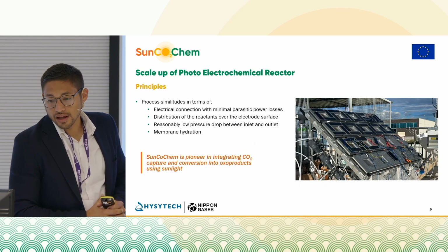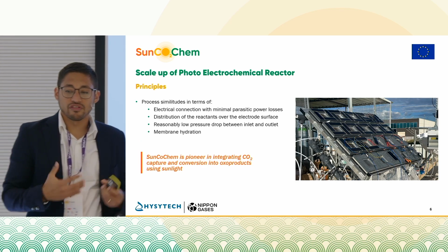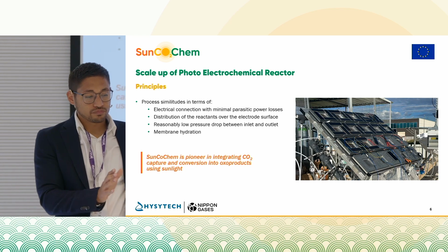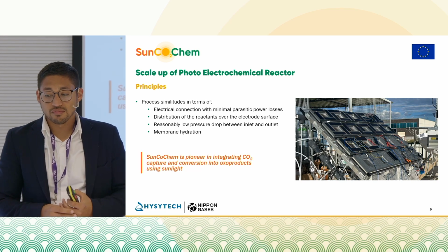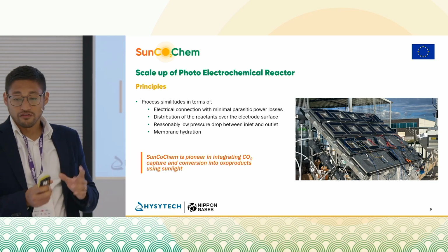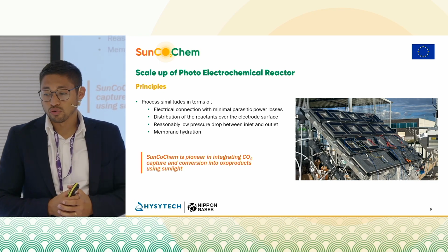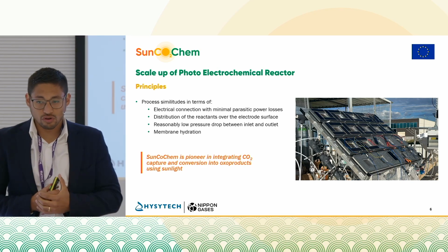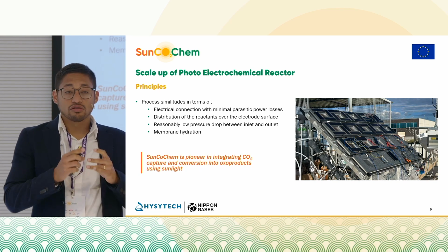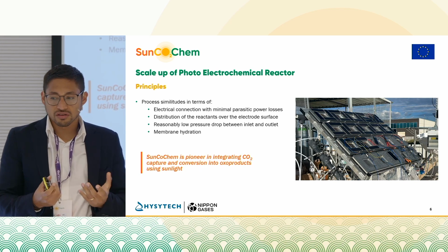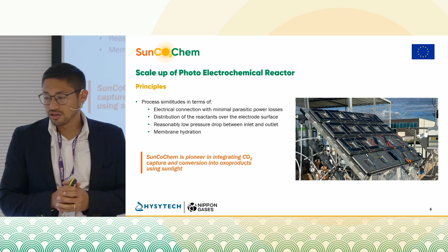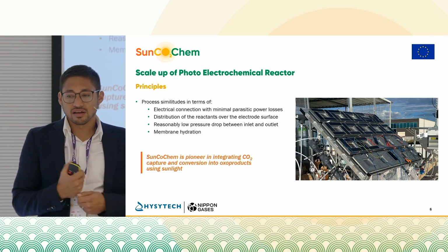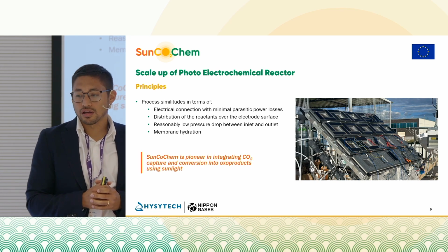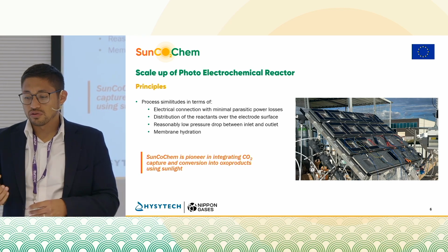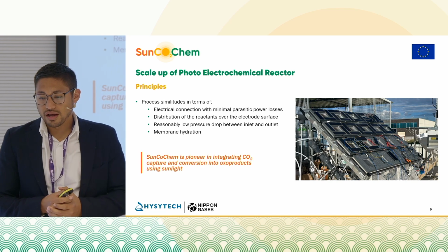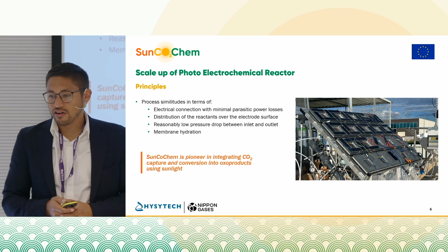The principles that we follow for the scale-up of the photoelectrochemical reactor are to try to bring the same process similitude of the system from the lab to the real scale process. So: electrical connection with minimal parasitic power losses, distribution of the reactants over the electrode surface so we can have a homogeneous process among the entire reactor. For this, it's important to have a very good fluid dynamic distribution, low pressure drop between inlet and outlet for each one, and membrane hydration. These are the principles that we have followed so far.